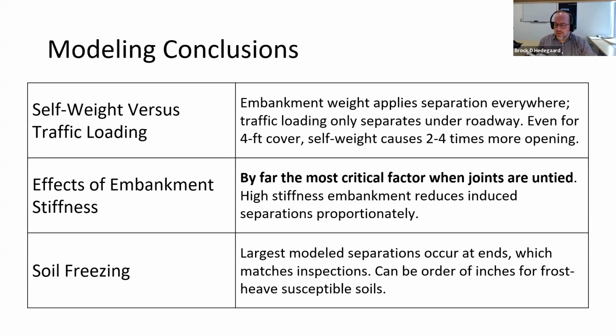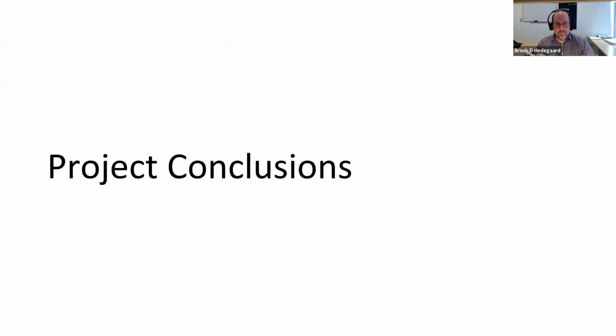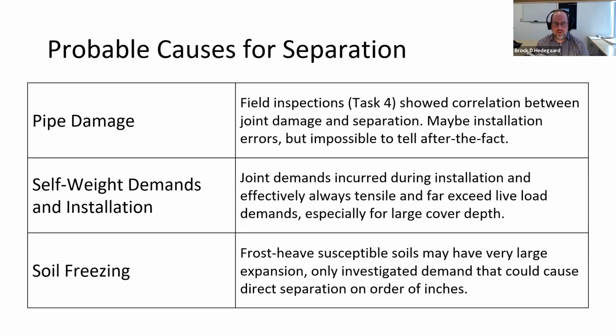And then soil freezing was really the only action that we looked at that could have orders of magnitude, like inches of separation, at those joints. So that was our most likely cause, that or just other large soil movements. So overall conclusions of this project, pipe damage was quite often correlated with what we saw in our field inspections. So again, maybe that's an installation error, or it happens after the fact. It's impossible to tell. But as a general rule, pipe separation or joint separation does seem highly correlated with a